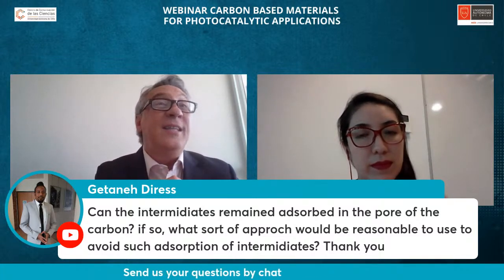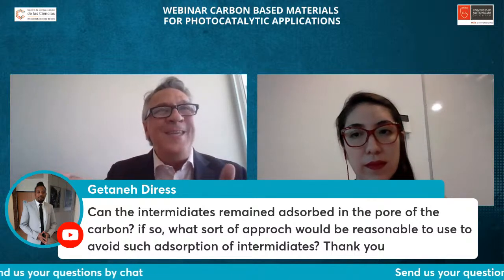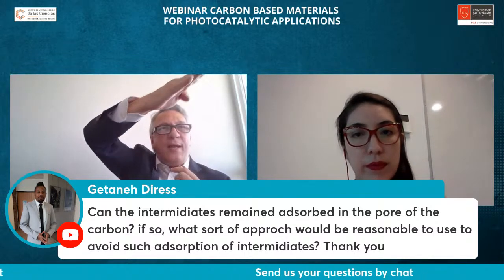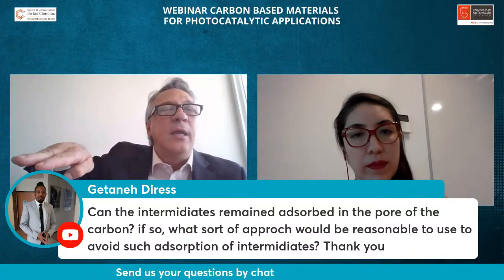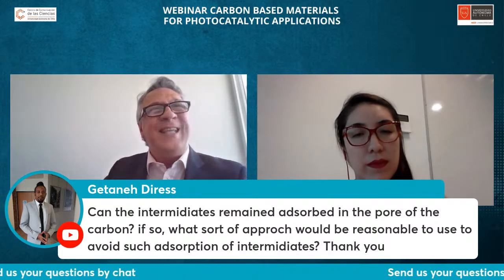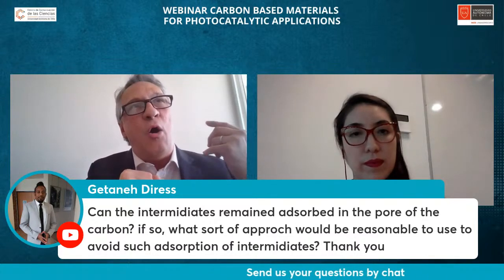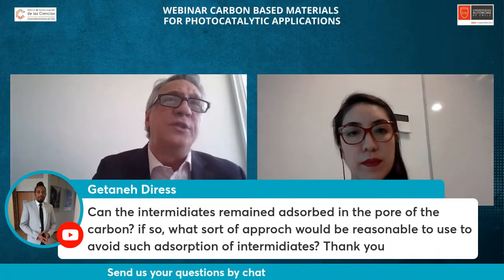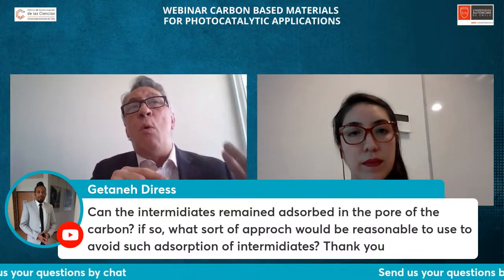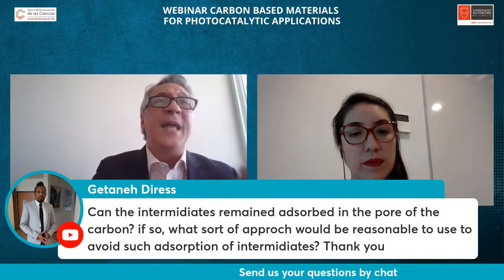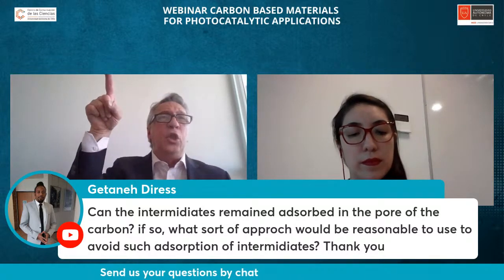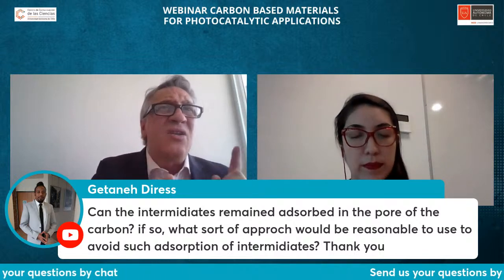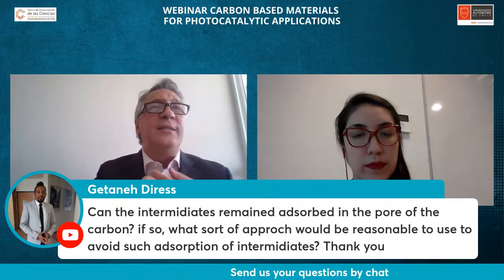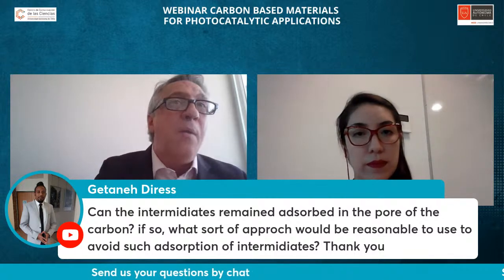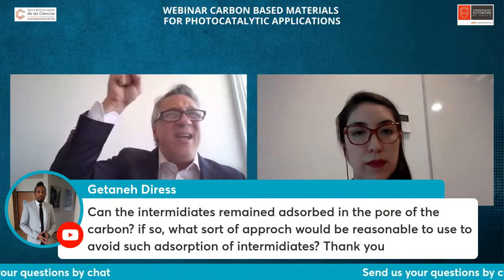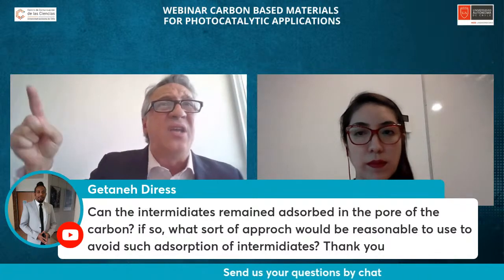And of course, this is heterogeneous catalysis. If you have a problem in the step of the adsorption, the reaction can go very well and readily be deactivated. And the reason is because the accumulation of intermediates starts to compete with the original pollutant for the active sites, for the adsorption sites. So that is the reason why it's so important to do the adsorption isotherms first, because the adsorption isotherm tells you exactly what the initial concentration and the loading of your catalyst have to be for your degradation experiments. Because if you select a very high concentration with a very high surface coverage, what's going on?